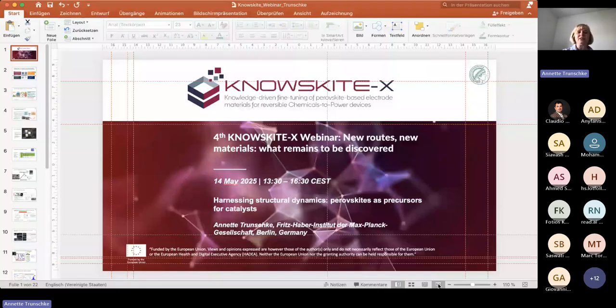We studied this here just by reducing in hydrogen and oxidizing in oxygen, and we observed that in the reduced state the cell volume is bigger, and in the oxidized state the cell volume is lower. This is a little bit different depending on the copper content, but it is not a linear relationship between the copper content and this behavior.